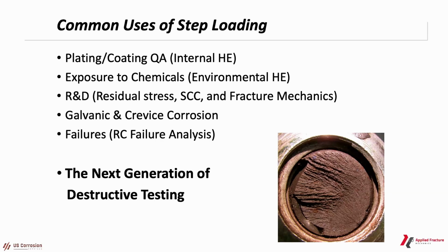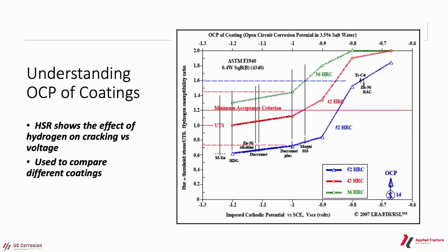And then we're also using it for research and development, looking at how hydrogen embrittlement is affected by things like galvanic and crevice corrosion, as well as failure analysis. So here's an example looking at the OCP of coatings and how this affects their hydrogen embrittlement performance. What I'm showing you here is kind of a complex chart, but we have 3 different strength levels of materials. Each of these strength levels of materials, these are all steels, were coated with these different coatings. So we have hot dip galvanized, zinc nickel, Dacromet, magni flake, zinc nickel, titanium cadmium. And then what I'm showing here is the susceptibility ratio.